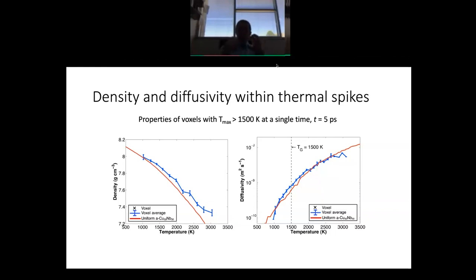So we see in this simulation, for instance, thermal spikes that were initially separated, cooling, but then the region in between those thermal spikes is such a small volume of material that it actually heats and it melts, right? So two initially disjoint thermal spikes are individually cooling, but are actually melting the material in between them. So eventually they merge into one thermal spike, and then that thermal spike cools. So you get these complex interactions with neighboring thermal spikes, which also influence the temperature field.